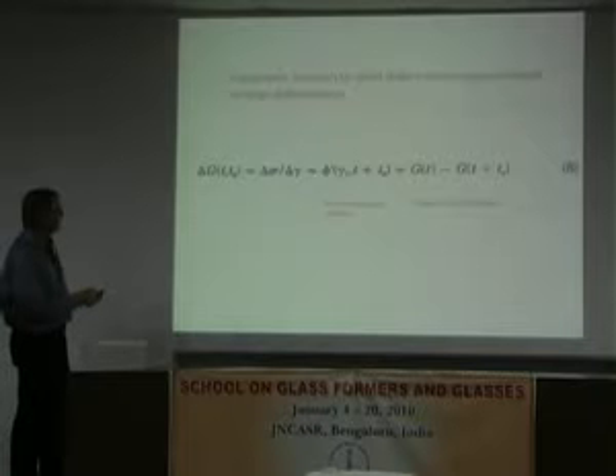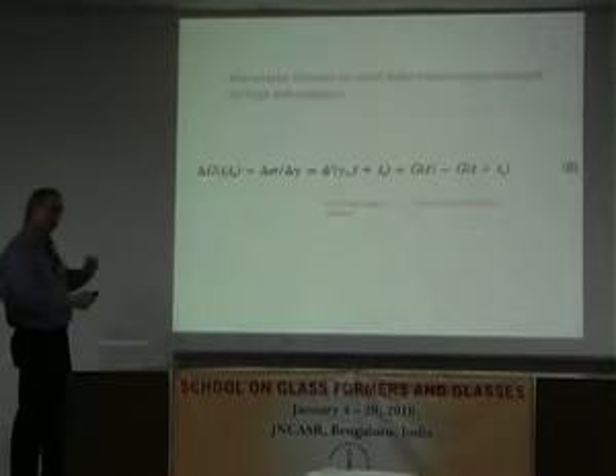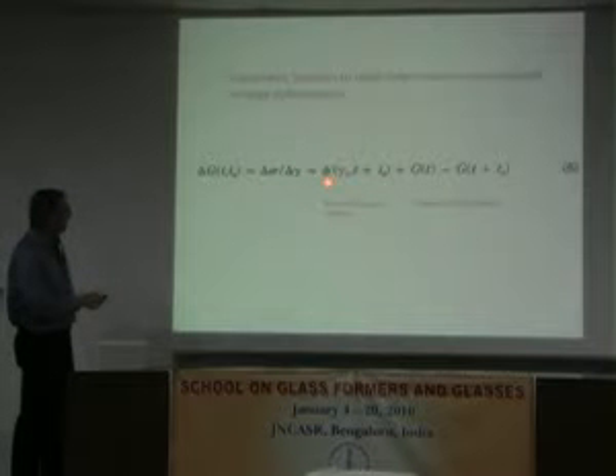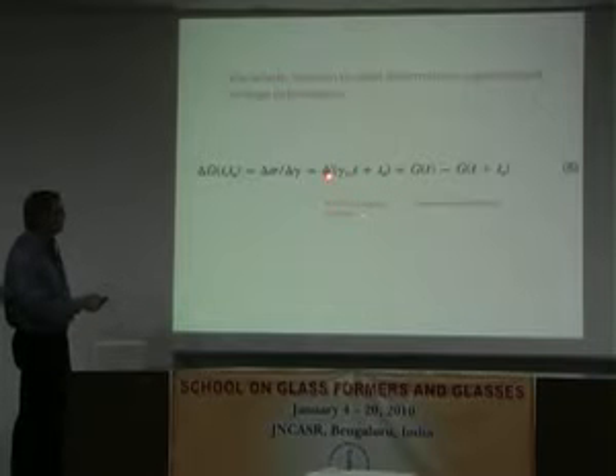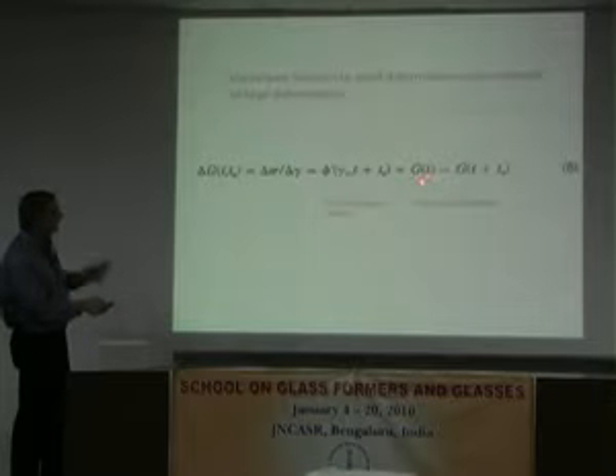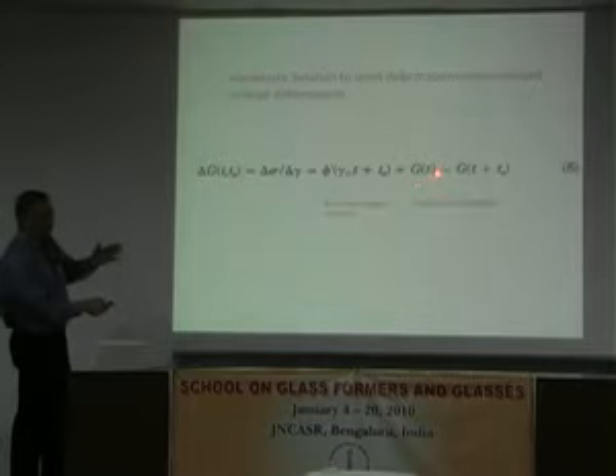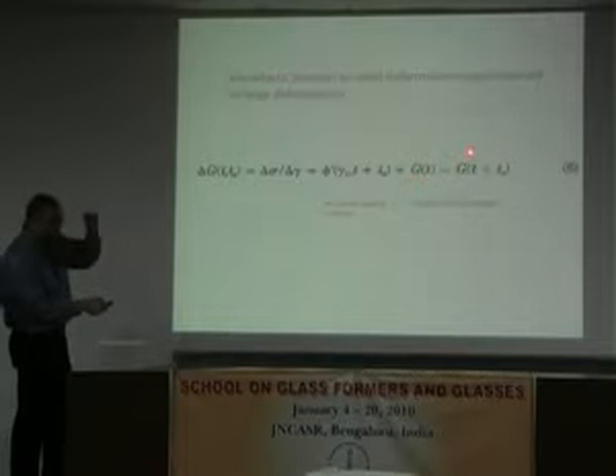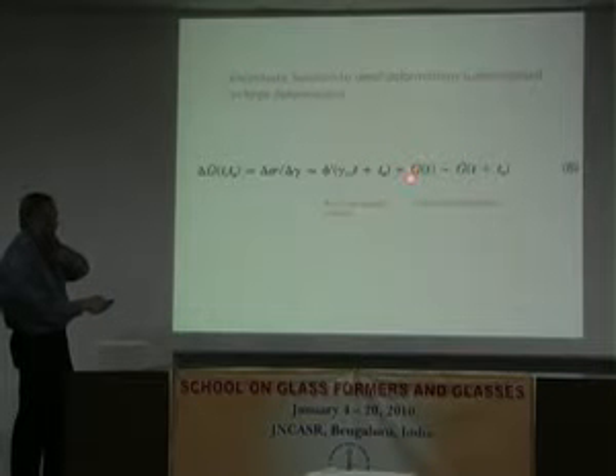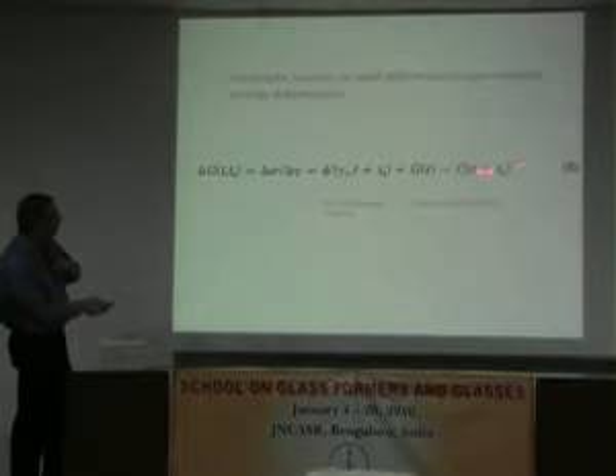It's just defined as delta sigma over delta gamma, so the incremental modulus. And there are three terms. First, let's talk about these terms. This is the linear viscoelastic modulus at time t, after I put the small deformation on, not the big deformation, but the tickle deformation. So that's the time after I put the small deformation on, minus the linear viscoelastic modulus at t plus the aging time, which of course is basically at the aging time.